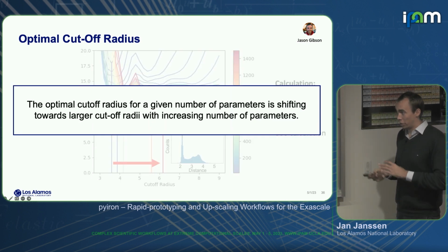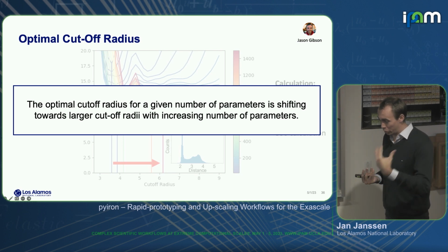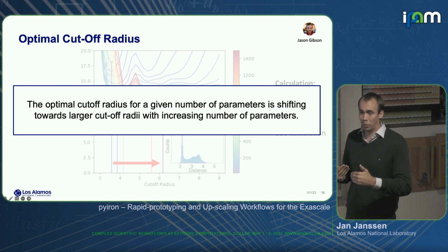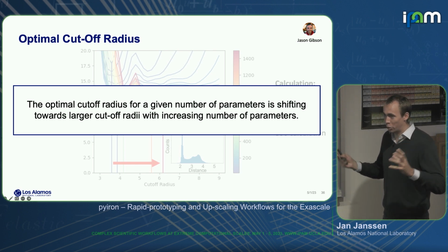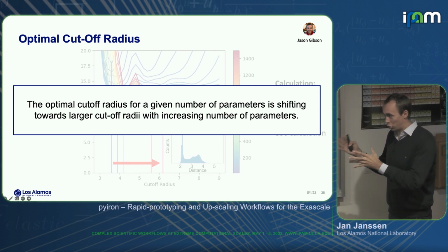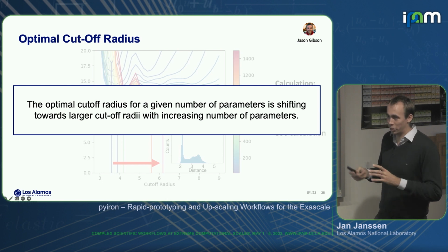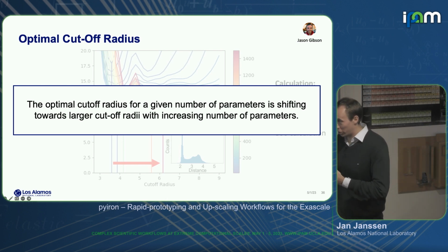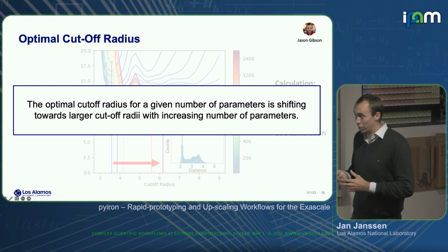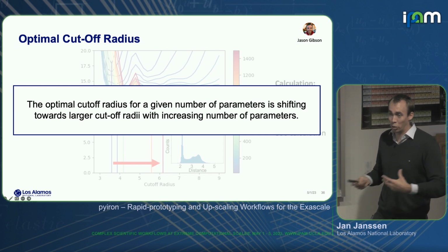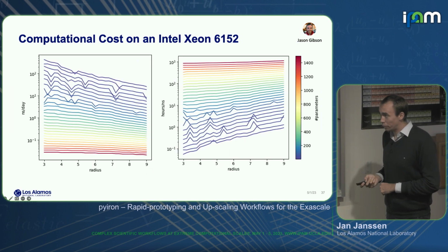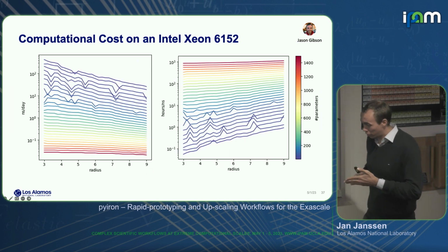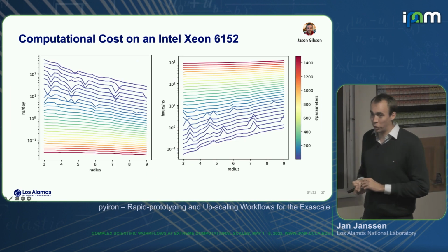Right, so what we feel here is that tools like pyiron help us to identify where there was a human bias, right? We always say, okay, we're physically motivated, we know how the cutoff should be defined, it should be just the second or third nearest neighbors. But now, doing these kinds of parameter studies, we really find the cutoff is a much less physical and more numerical parameter, and it's about how to optimize it. Talking about this parameter study, we also looked at the computational cost.